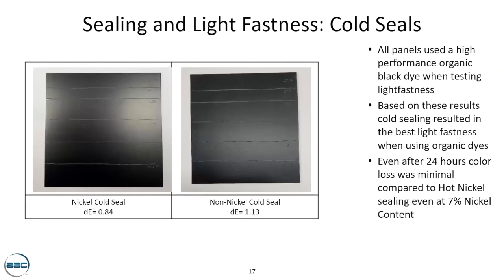Cold seals. So we used 2 cold seals. One was a nickel cold seal and the other one was a non-nickel cold seal. As usual, these parts were made with high performance organic black dye. Based on these pictures, you can see that the cold seal resulted in the best light fastness durability while using organic dyes. Even after 24 hours of accelerated light fastness test, the loss of color was very little as compared to a hot nickel seal, even at a concentration of 7% nickel content in the seal.